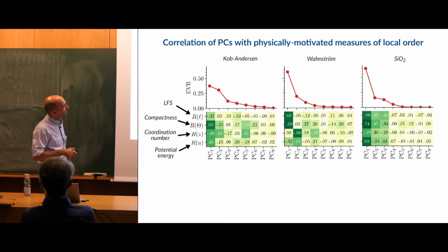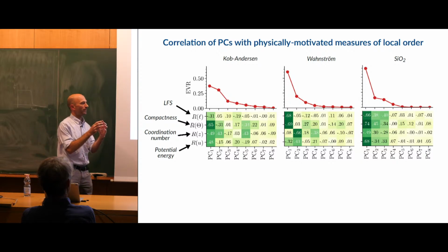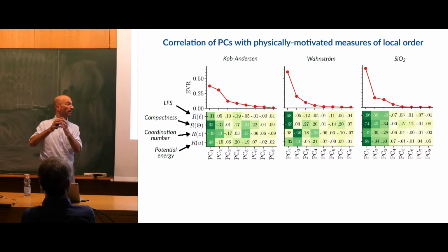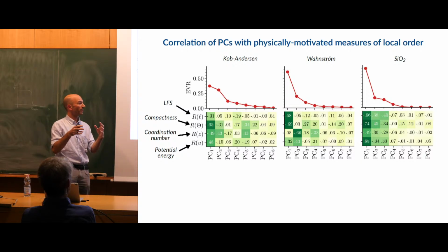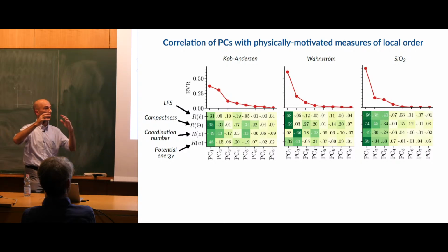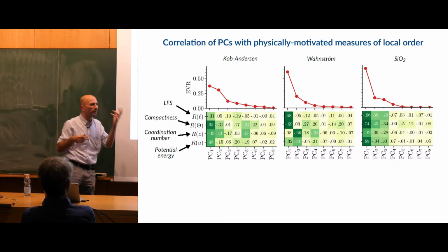Another thing to support this idea: you see that the LFS is always correlated to the first principal component, even in the Kob-Andersen mixture. But here, the correlation is simply not strong enough for these structures to stand out from the bulk of the disordered local arrangements. So there's a weak correlation, but it's not strong enough to detach it from the bulk. In this sense, it's not well defined as a locally favored structure.